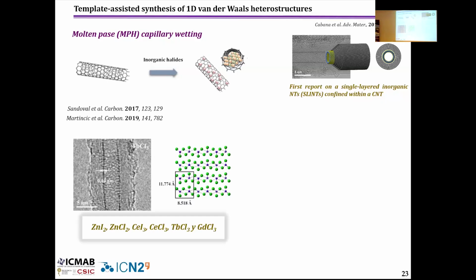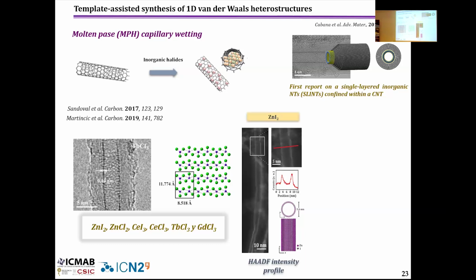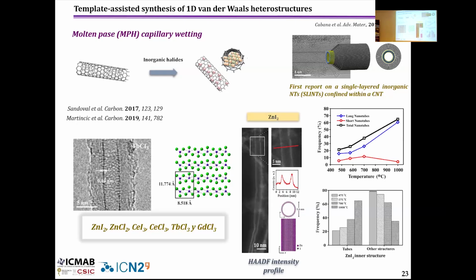So then what we did is try to extrapolate this synthesis to a variety of inorganic halides. So we were able to use different solid van der Waals solids that include zinc iodide, zinc chloride, cerium compounds, terbium compounds, gadolinium chloride to prepare these heterostructures. So these systems were characterized using high-resolution microscopic techniques. And we also studied the possibility of tuning the ratio between the tubular structure, which usually is very low. So because usually the formation of solid crystals inside carbon nanotubes is favored.